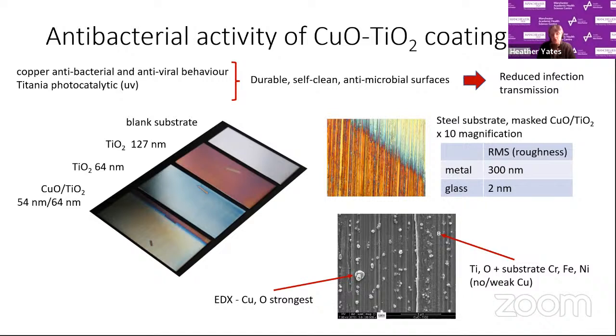Putting layers on and dealing with microorganisms on steel is more challenging. If you look at the optical microscope times 10, you can see a lot of striations from the steel. It's much rougher than glass. The roughness can be measured, root mean square. Metal is so much more rough at 300 nanometers as opposed to glass at 2 nanometers. So you can see the challenge because the microbes can obviously hide within those striations, making it more difficult to kill them.